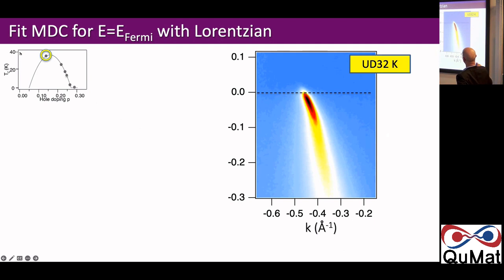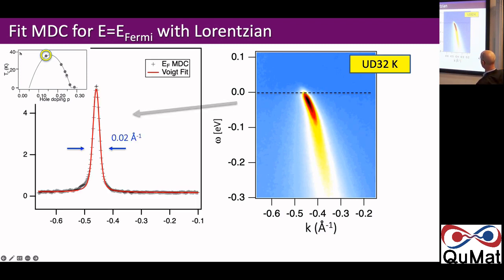Okay, so what we're doing, this is an example for the highest TC sample we measured. This is just one half of this distribution. We measured both sides. And then if you cut this at the Fermi energy, you get this very narrow object. Of course, in principle, if this was a Fermi liquid and our sample was perfect, this would be a delta function. Of course, I can't measure that, so it's a delta function broadened by my instrumental resolution and also by things like impurity scattering in the crystal. So this is essentially as close to 0 width as we can get it for these kind of materials. So this is a fit with a Lorentzian curve, which is what you expect from this kind of spectral function, convolved with the Gaussian, which is our resolution, that gives you something called a Voigt.